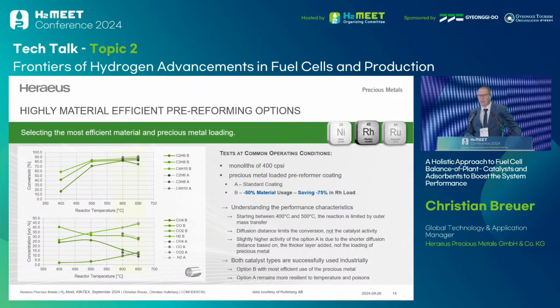Of course, this is just an add-on. Rhodium, as I mentioned, is of course a valuable material, but depending on the conditions and how well we understand the overall system conditions, we have shown in studies that with these materials, compared to the workhorse formulation I just showed you on the previous slide, in other applications we could go to operations with, in this case, 75% less rhodium than the previous one, and still reach the desirable operation regime. So understanding the material and understanding the system will also help improve the material efficiency here.